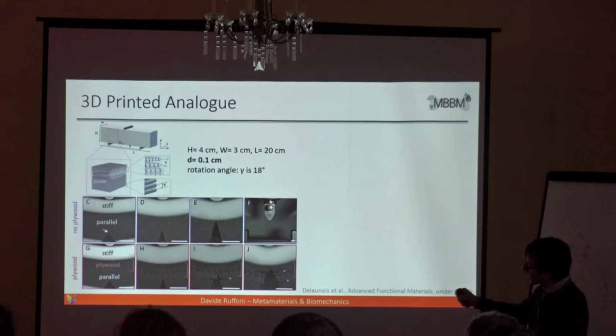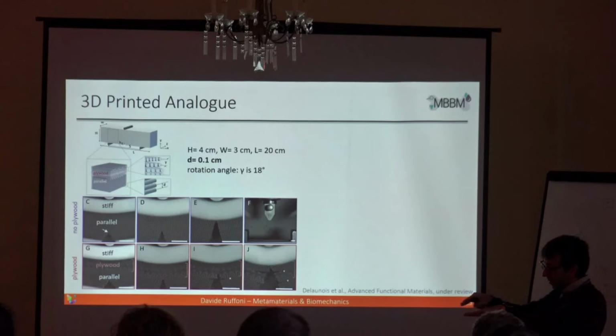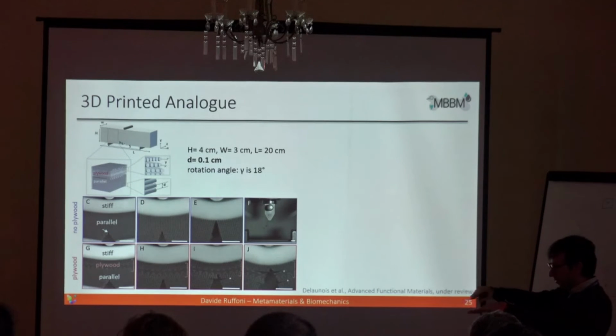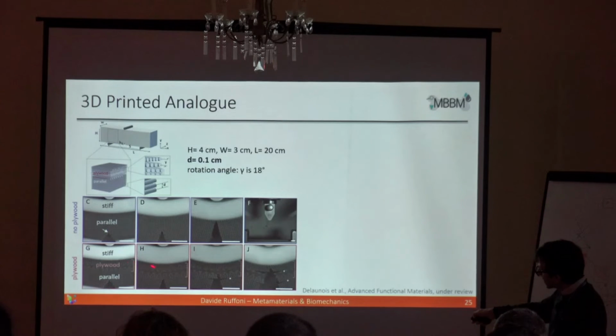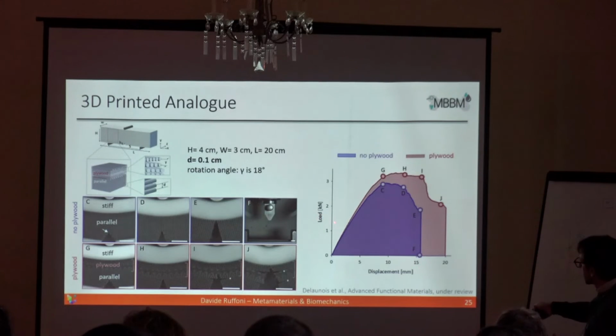So we added a thin interfacial layer with fibers arranged according to a plywood, so with a different organization. And what we see is that this is quite efficient in interacting with damage. As soon as the damage starting from the notch reaches the plywood, we see some delamination, which dissipates quite some energy, and further propagation of the damage again dissipates quite some energy. Macroscopically, the load displacement curves are quite different, and when we insert the plywood, we can absorb a little bit more energy before breaking the system.